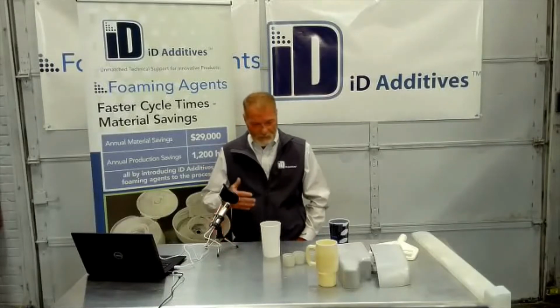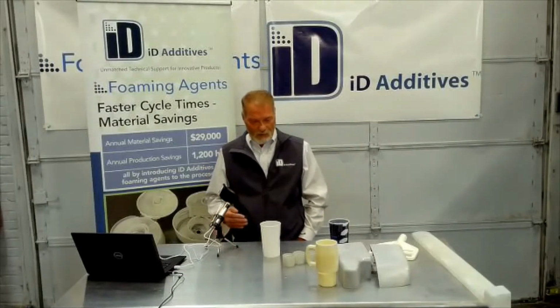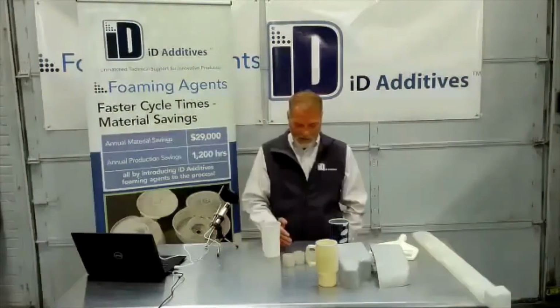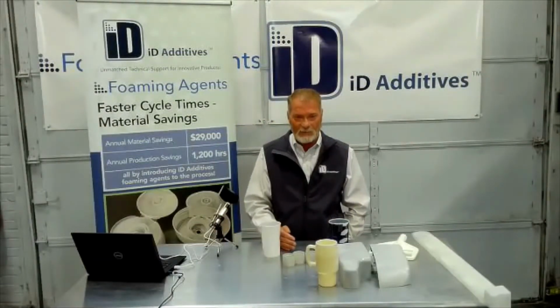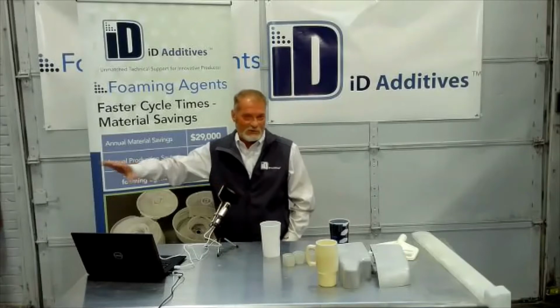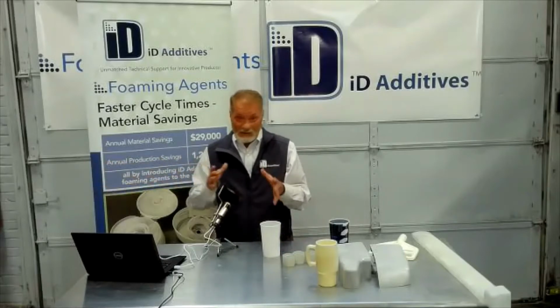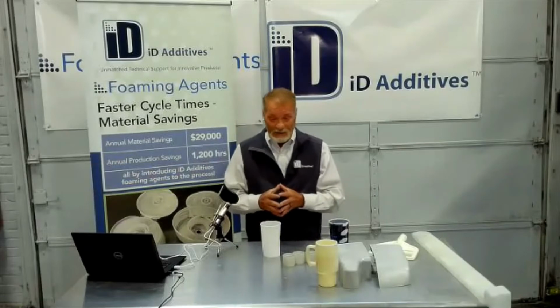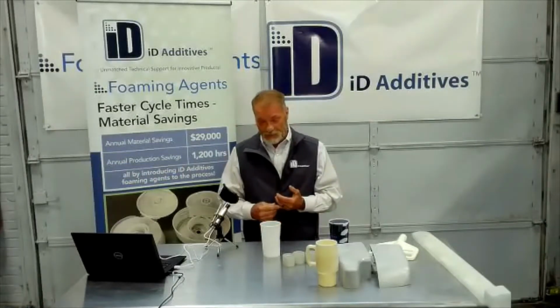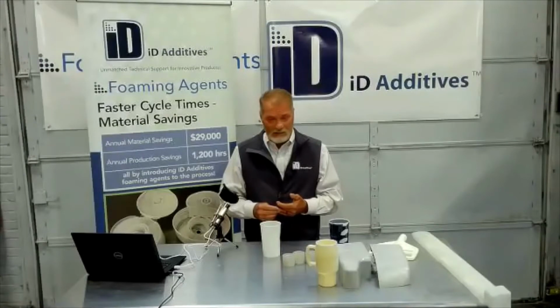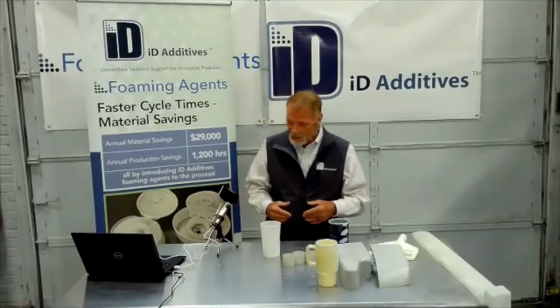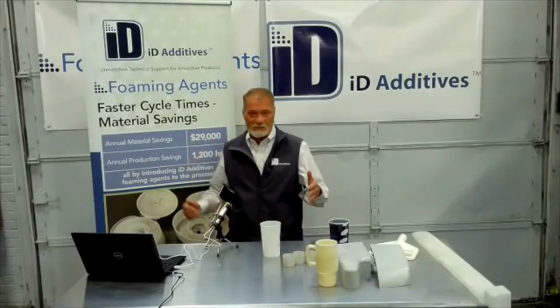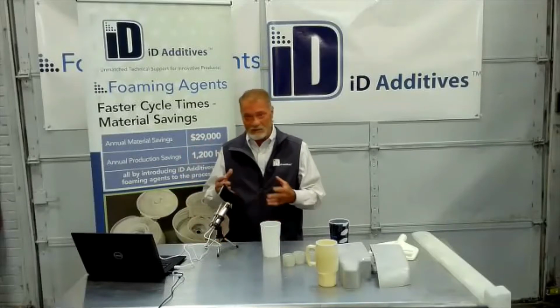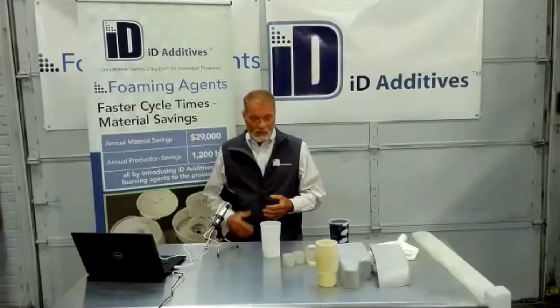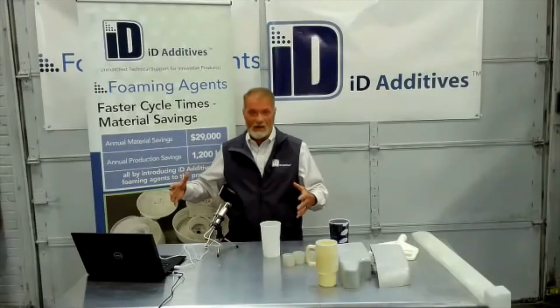So we really want to get to the point where you're asking questions or you want to set up a call to go over your application, because your application is different than the vast majority of applications. Everything is a little different. Process-wise, it's still low pressure. You still want to keep everything moving. That's residence time. Whenever you're running foam, you always want to get that screw back just before the mold. You don't want that gas in the rear, it disappears. So you don't want to have it set back there forever.